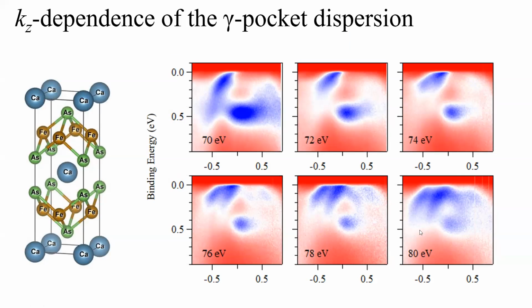You continue, please. But with cobalt doping, we are seeing that somehow this gamma band actually gets a significant amount of kz dependence also. It has kz dependence also. The other thing that we see is that while in the parent compound, when we did the ARPES measurement, we observed that the dispersion of all these bands remains the same at different photon energy or different kz values. However, in this case, the dispersion of the gamma band actually varies with different photon energy or different kz value also. So this is the third observation that we have in this compound.